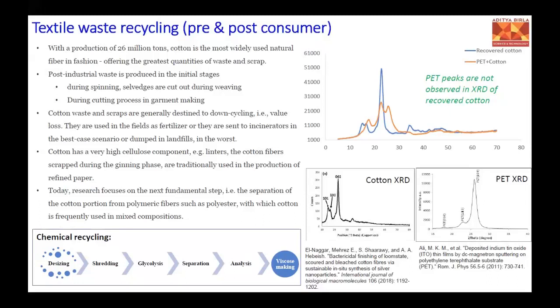And basically we use this cotton in our viscose. Again, the catch is that we cannot use it 100% because, as I told, there are certain impurities at the ppm level. The major thing that we have observed is that even after the separation, some ppm level polyester remains in the pulp, and that causes a filterability issue. And there is another coagulation of the polymer solution that is being formed.